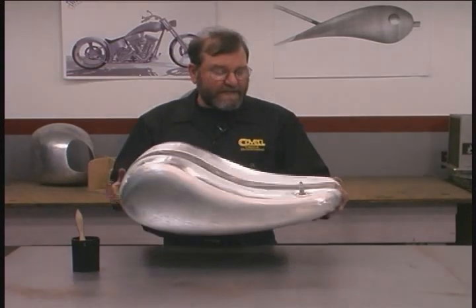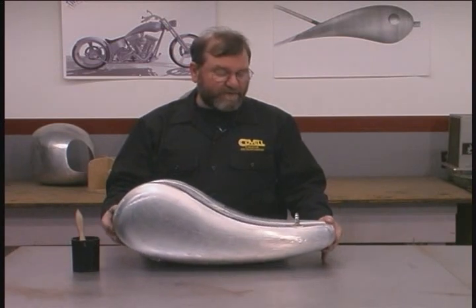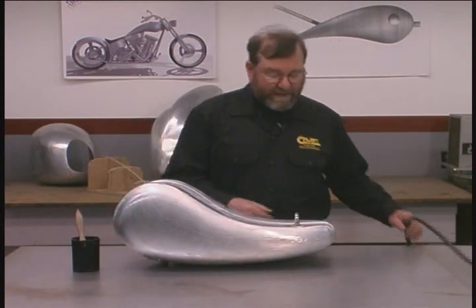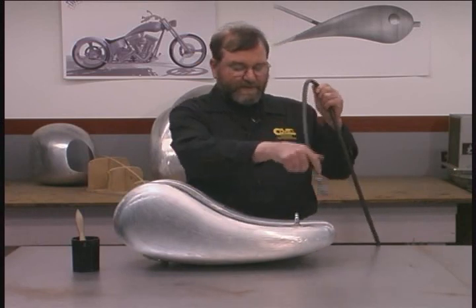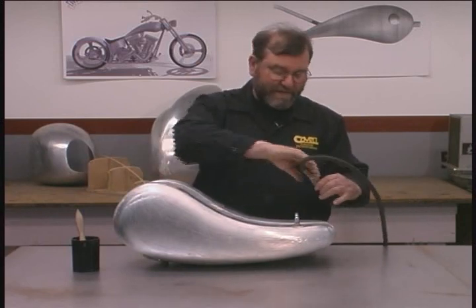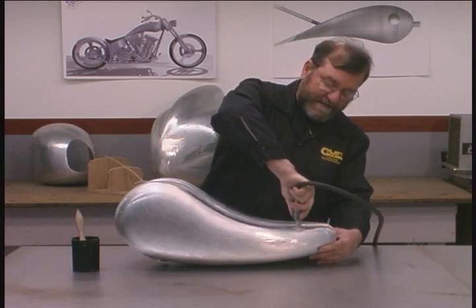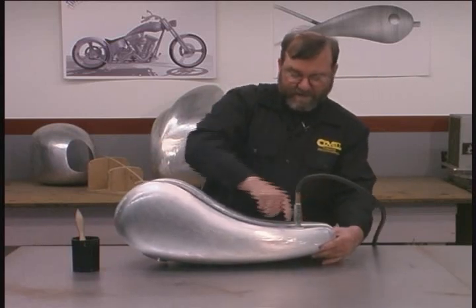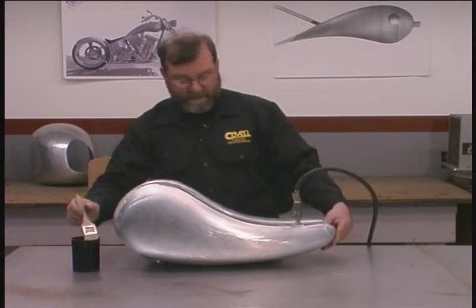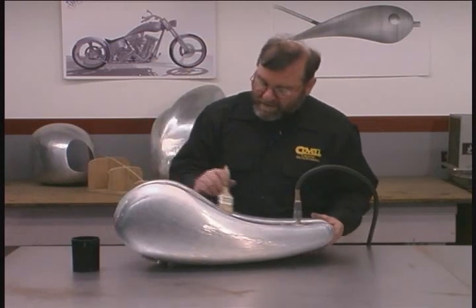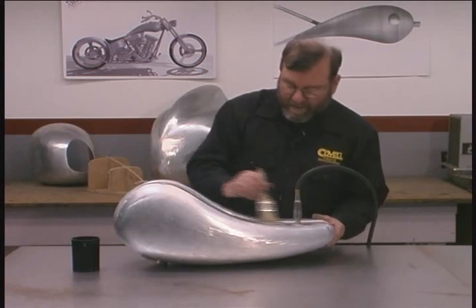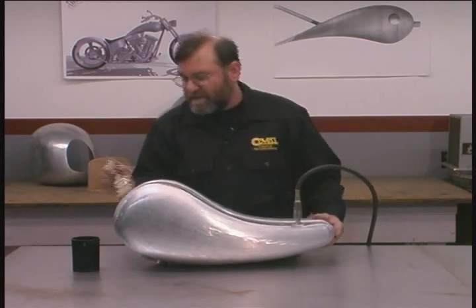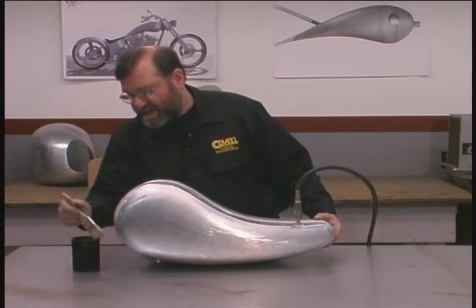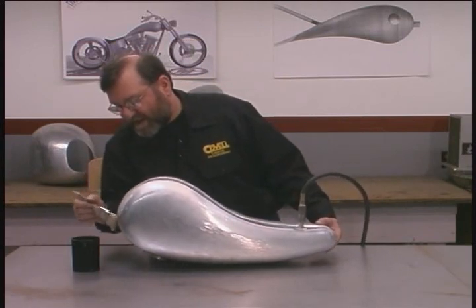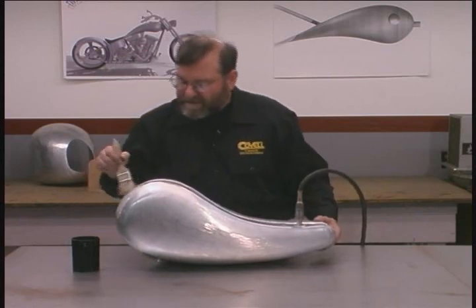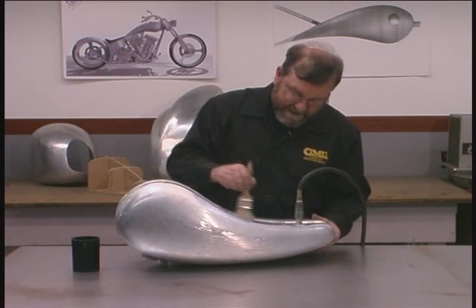Once all the welding is completed on your tank, it's very important that you check it with pressure for leaks. And when doing this, you must be sure to not use more than 2 or 3 psi, otherwise you can balloon out the tank. So we'll connect the air line to the tank. I've put a fitting in the location where the petcock would go. And we'll start brushing over the seams with a soapy water solution. Should we have a leak, what you would see would be a lot of little bubbles forming. Actually, I did find a little leak here. Let's continue, see if there are more leaks.